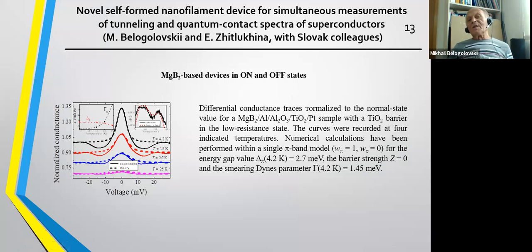The next thing relating to contact spectroscopy is our attempt, together again with Slovak colleagues from the Bratislava University, to fabricate a device where you can switch between tunneling and point contact regimes of spectroscopy. It's known that to observe the energy gap and phonon structure in a tunneling regime, you need a barrier between the injector, a counter electrode, usually normal, and the superconductor studied. And in a point contact experiment, you need a direct contact between the tip and the superconductor.